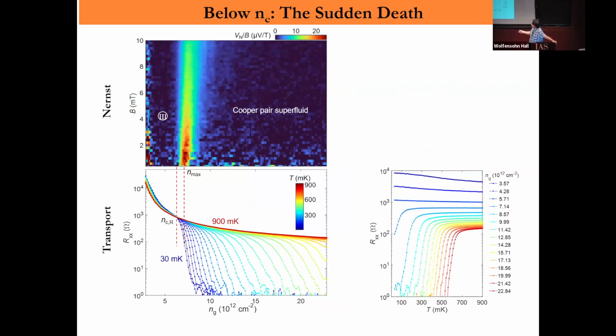So I'll just quickly go through the data here. Another interesting data is what happened in regime 3 in the resistance. In this case, it's a metallic-like state. What I'm plotting here is the Nernst fluctuation signal as a function of gate and B field, normalized by B. You really see the fluctuation is a property of zero B, even though I need some B field to measure it. Also the resistance measurements correspondingly - here you see the fluctuation corresponding to this regime, but suddenly everything disappeared in this regime. This normal metallic regime has a resistance of about 1 kilo-ohm. It should, in principle, support fluctuation, but it didn't in this case.